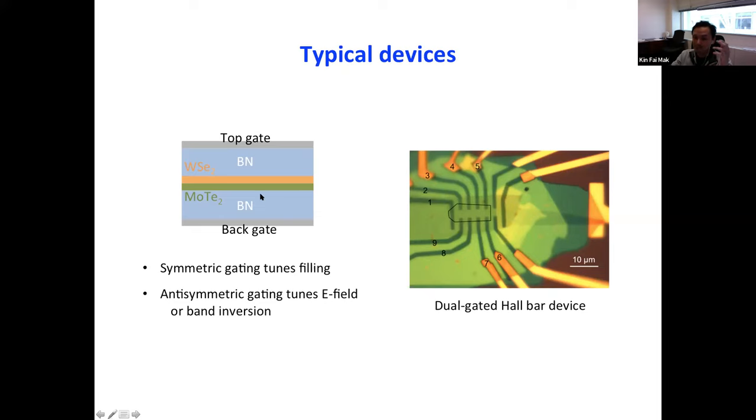Compared to the absolute density, this moiré density is high. So all these factors would just make the formation of contact good. And finally, I would just mention that we are putting a top gate, then applying a huge electric field to the vertical heterostructure. What that means is that we dope the materials heavily around these electrode regions. So all this is by design, and it makes very good contact in the system when you apply a large electric field.